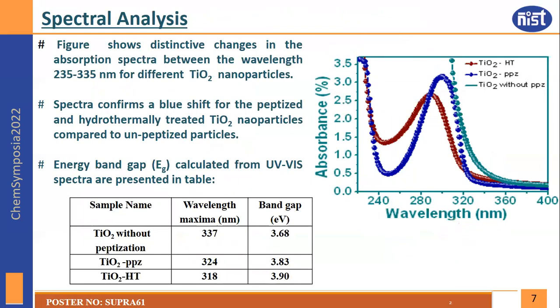The spectral analysis through UV-visible spectroscopy shows the hypsochromic shifting of absorption maxima, which confirms the formation of smaller size particles on peptization and hydrothermal treatment compared to the unpeptized one. The energy band gap calculated from UV-visible spectra is presented in the table below, which shows the band gap of the developed materials at different absorption maxima.